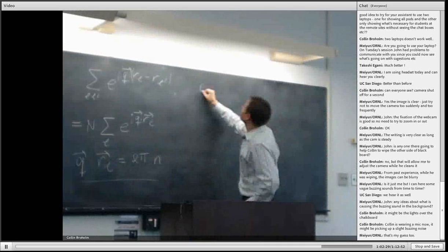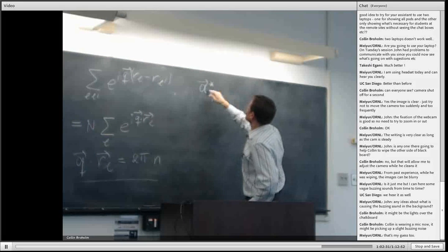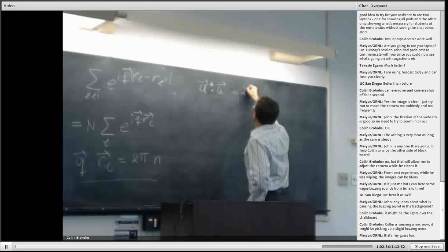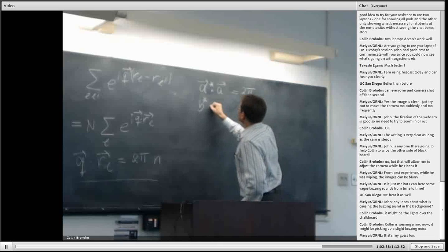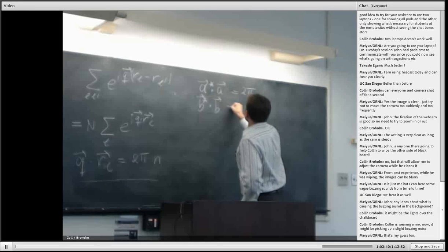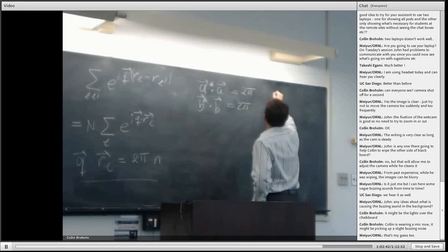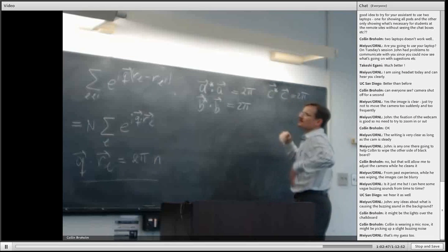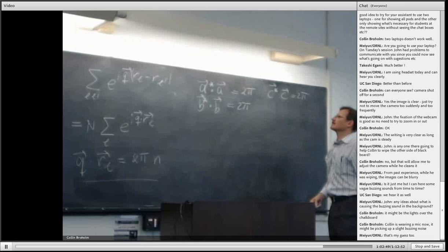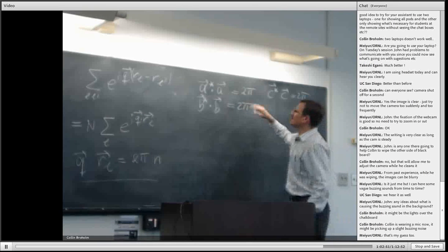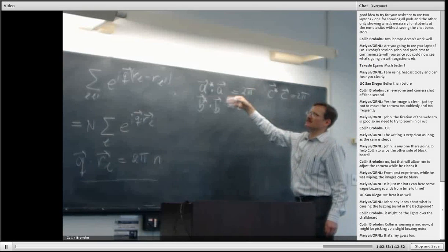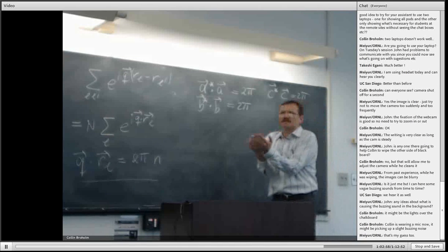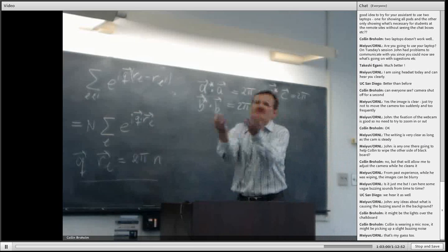And then we're going to define the reciprocal lattice in such a way that A star dot A equals 2 pi, B star dot B equals 2 pi, and of course C star dot C is equal to 2 pi. So this will define a so-called reciprocal lattice. Whenever I give you A, B, C, you should be able to derive an A star, B star, and C star. We won't spend a lot of time saying exactly how you obtain those vectors. The most important thing is that it's possible to obtain those vectors.